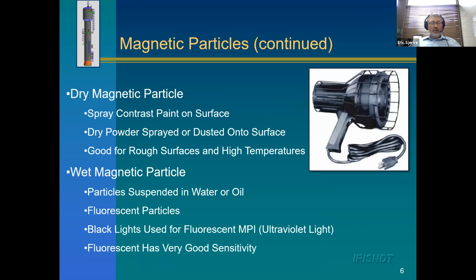For magnetic particle, we have two ways of doing it. We can do what's called a dry magnetic particle inspection. That's where we spray a white paint on the surface and we use a powder that's dusted on the surface. That powder will congregate where we have the defects that break the surface, and we'll visually see the defect. This is good for rough surfaces, and it's good for high temperatures because there are no liquids to boil off. We also use wet magnetic particle inspection, and that's a higher sensitivity technique.